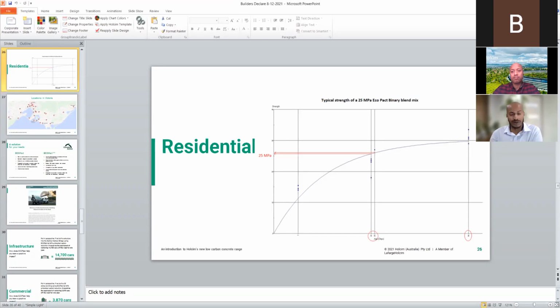The reason I brought this graph up is to show you what we can achieve and some of the limitations that we work around. Typically, concrete strength is guaranteed at 28 days. This is something most people are familiar with, whether it be 20 MPa at 28 days or 40 MPa at 28 days. As soon as we make EcoPact with a binary blend, which is GP and fly ash, and we push that fly ash percentage as high as possible, so it falls within the window of what EcoPact is, and reduce that embodied carbon between 30 and 60%.